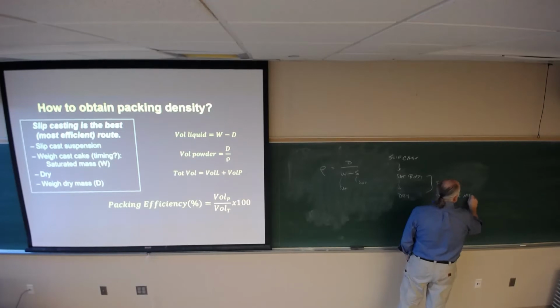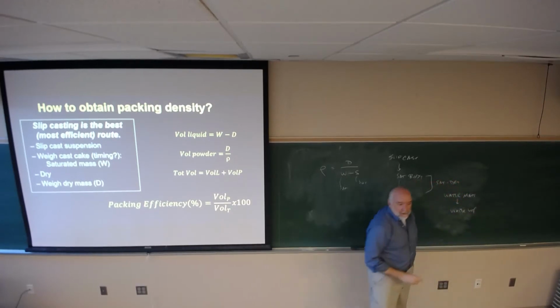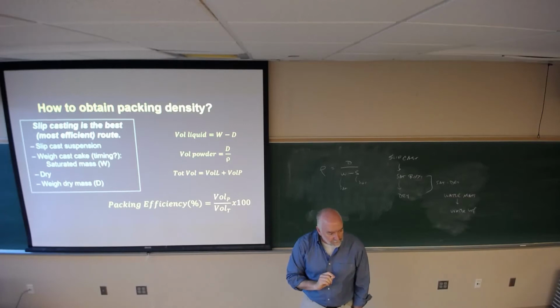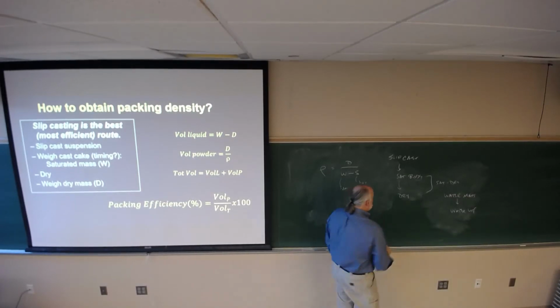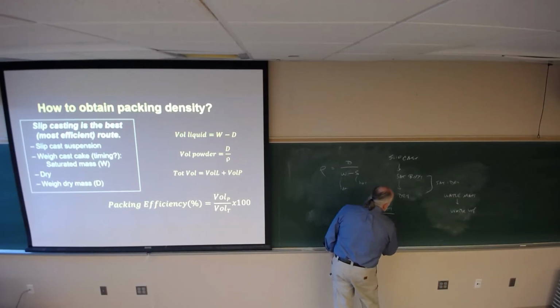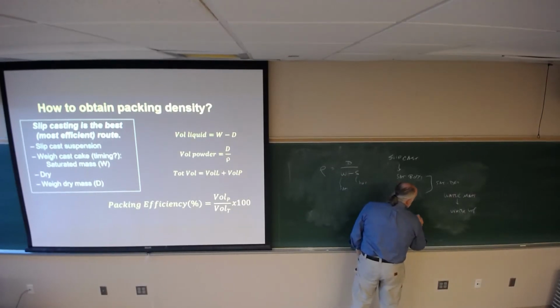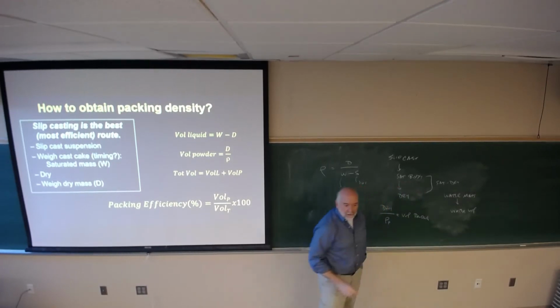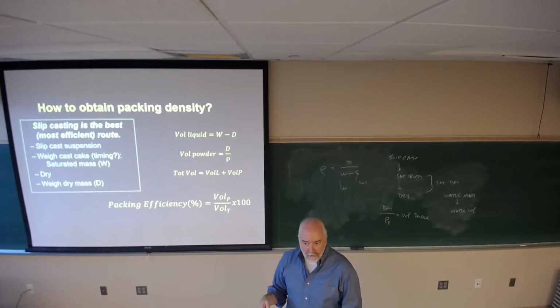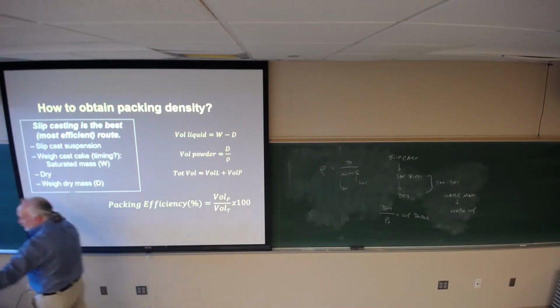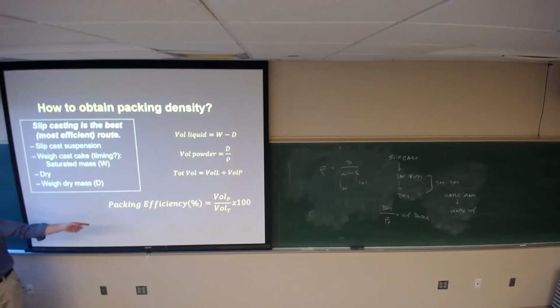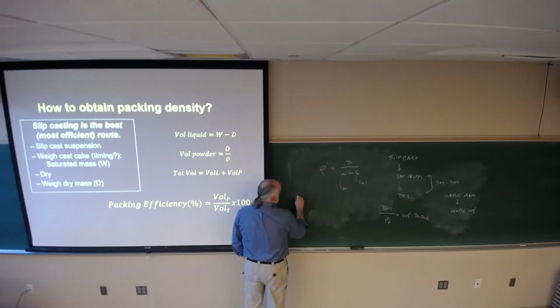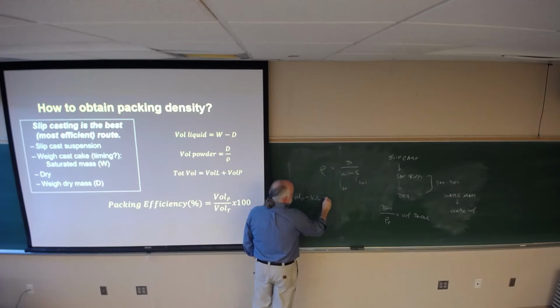Now it's a mass, but knowing the density, I get the water volume. That water volume is my pore volume in the system. If I take the dry mass and divide by the density of powder, that gives me the volume of powder. So all I need to know is the density of the powder. How do I get it? Well, I could guess. If it's alumina, it's 4. If it's clay, it's 2.6. But I could also measure the density independently in a helium pycnometer and get the density that way. And if I take the volume of powder plus the volume of water, this is the total volume.